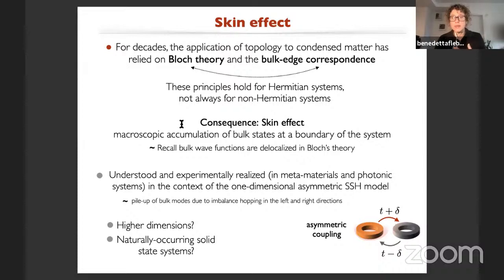And one of the consequences is that the bulk states cease to be Bloch states, become non-Bloch states, and start accumulating macroscopically at some boundary of the system. This was definitely well understood and realized in one dimension in this very simple model, that I would say is even trivial, when you tune the coupling in such a way that a wave function will travel more likely to the right than the left. But it's not yet fully understood in higher dimension, and has not, again, to my knowledge, been observed in naturally occurring solid-state systems that are not finely engineered metamaterials.